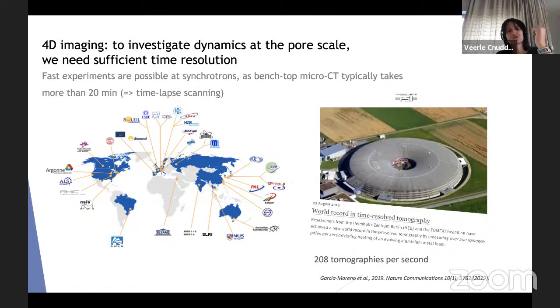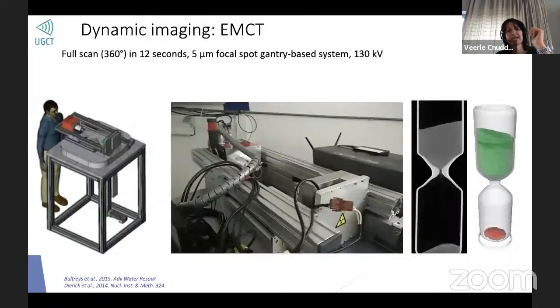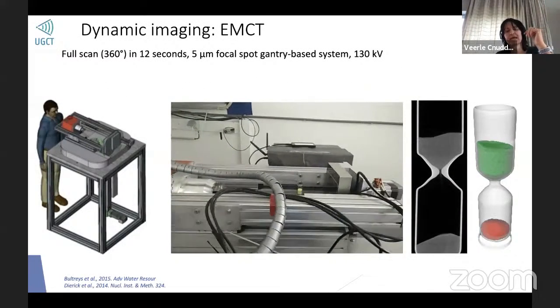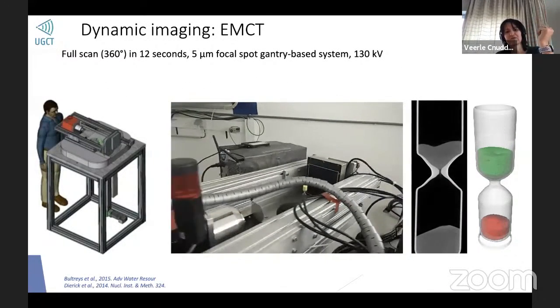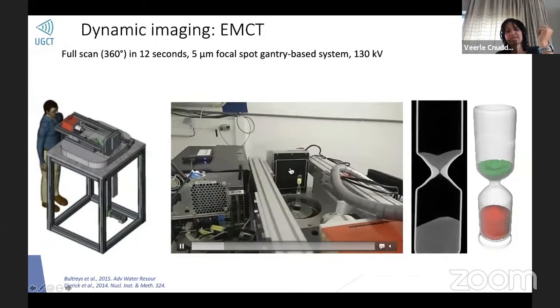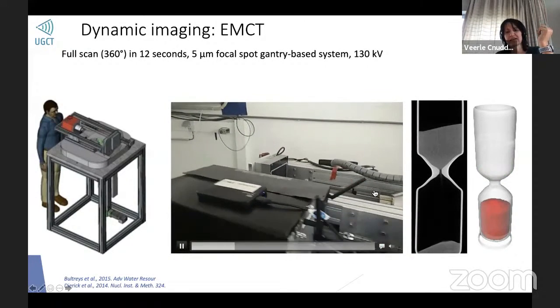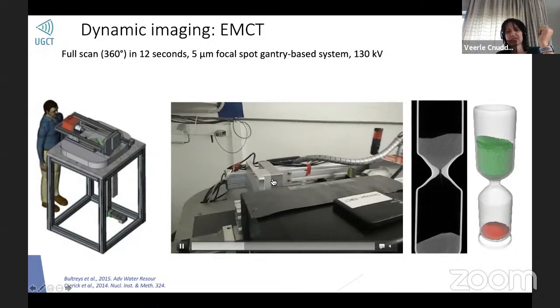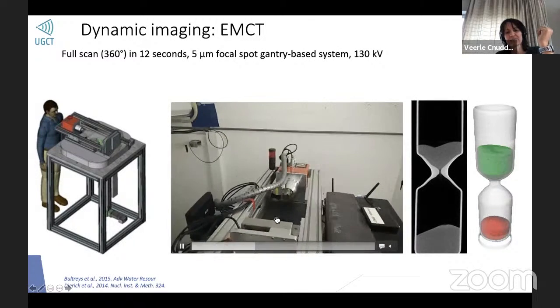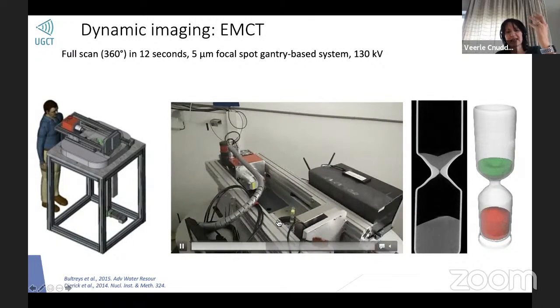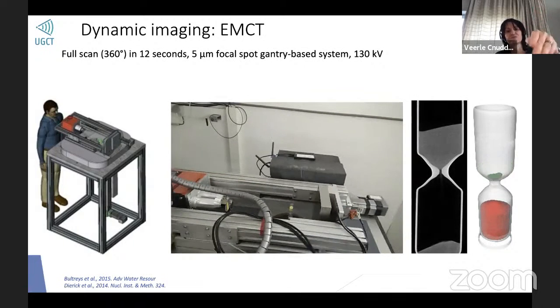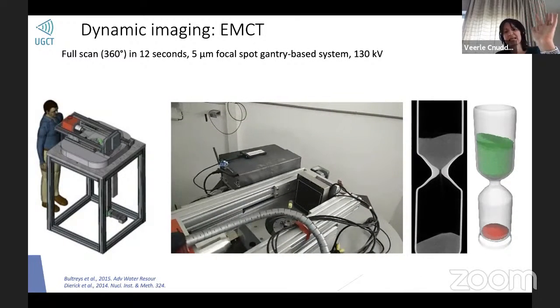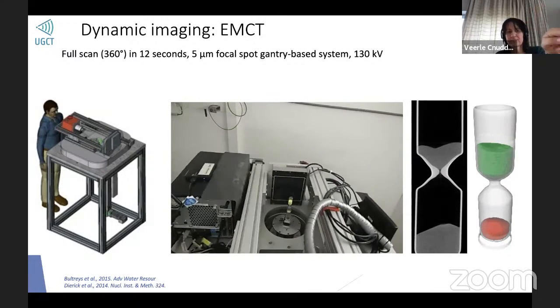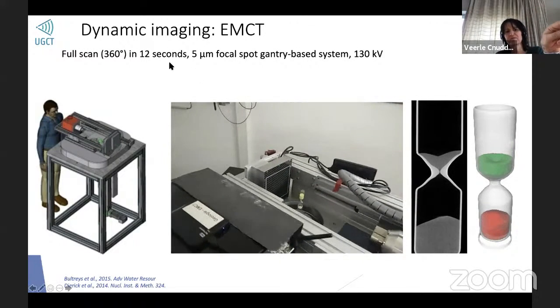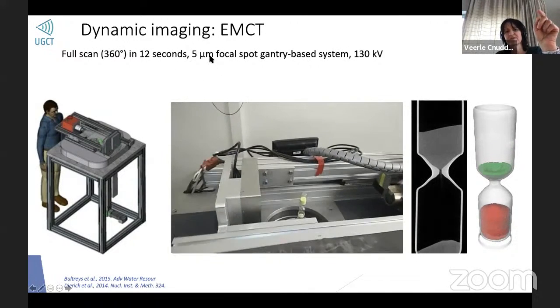But we try to find something in between, and that is why we developed our own environmental CT scanner for dynamic imaging. The idea is that we have a source and detector rotating around our sample, because if we want to scan continuously, with this system we can do continuous scanning of 20 minutes. The full scan takes 12 seconds and the focal spot is 5 microns.